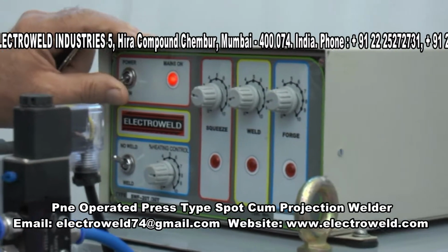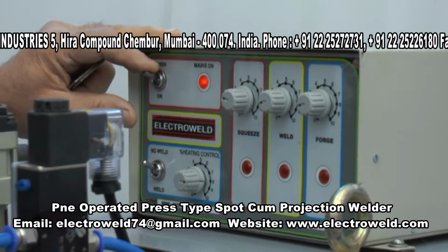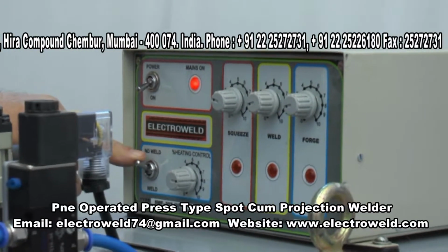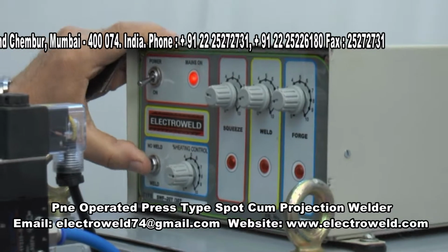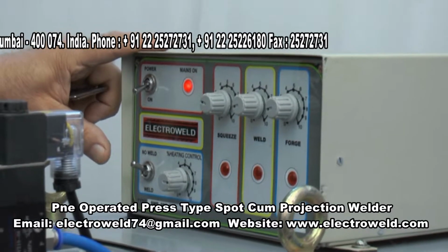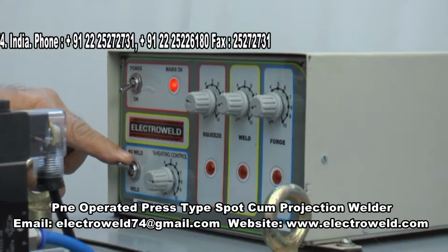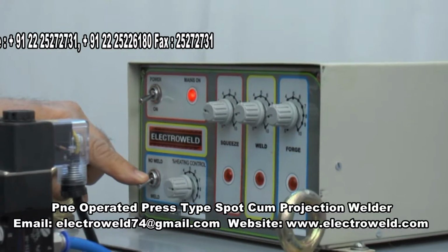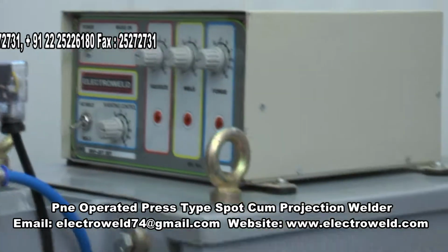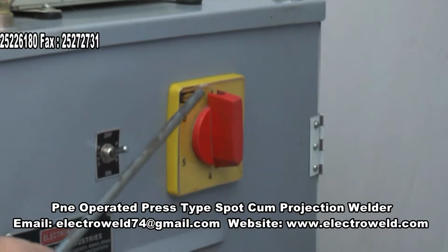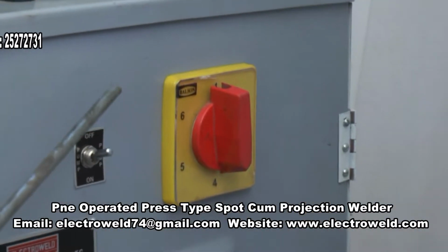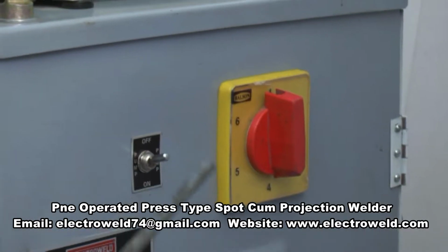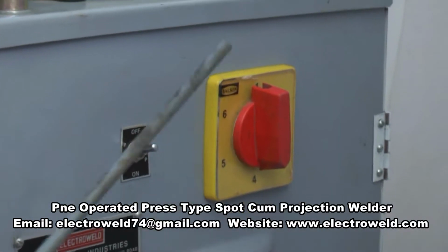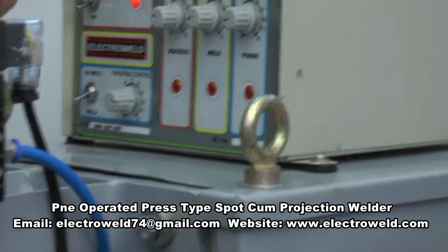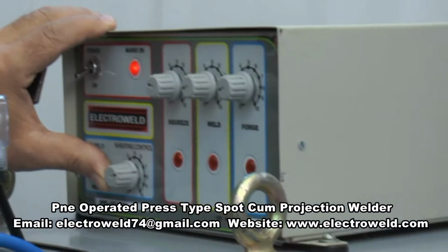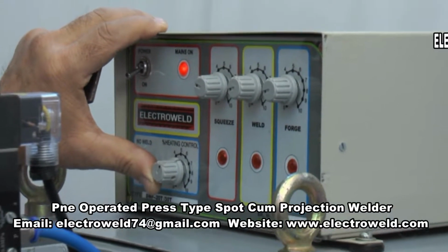This one here is the timer on off switch. This one here is a weld no weld switch. When you want to weld, you have to put the toggle switch towards the weld side. This over here is a coarse current selector switch. Depending upon the thickness of the sheets to be welded, you can adjust the current first over here. Then you can adjust this pot for fine setting of the spot welding current.